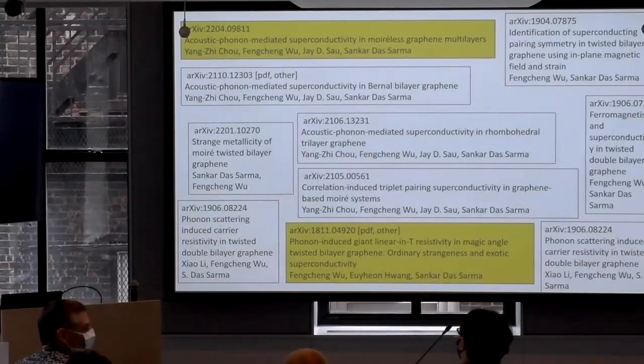I completely forgot about the negative intercept issue, because it used to be my pet peeve quite a few years ago, and not being in the middle of this, I kind of feel like if the intercept is negative, that suggests, at least it suggested to me, that the low temperature expansion is just misleading. Absolutely. You shouldn't take it, and maybe you should do a high temperature expansion. Yeah, you should. I have papers about that, but they never connected to experiments. So when you see a negative intercept, what's your instinct? This is of course a question I have faced several times. My honest answer is that I do not know of any regular theory which will give that, but I can create that with inhomogeneity.